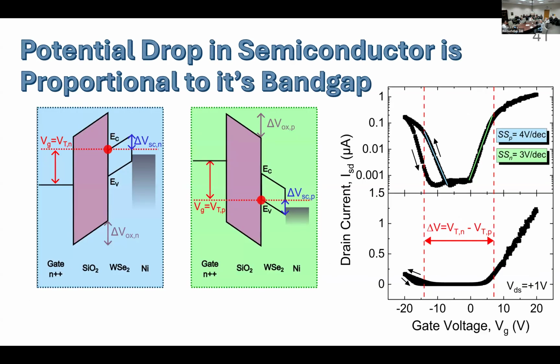So to further verify our use of the semiconductor thickness as the semiconductor depletion width, we are going to try to calculate the band gap value from our bipolar transfer curves. Like I mentioned before, the potential drop across our device can tell us about its band gap value simply by looking at where the onset of threshold is. At the onset of threshold, we have modulated the Fermi level to be at the top of the conduction band, or the bottom of the valence band, or the top of the valence band, bottom of the conduction band.